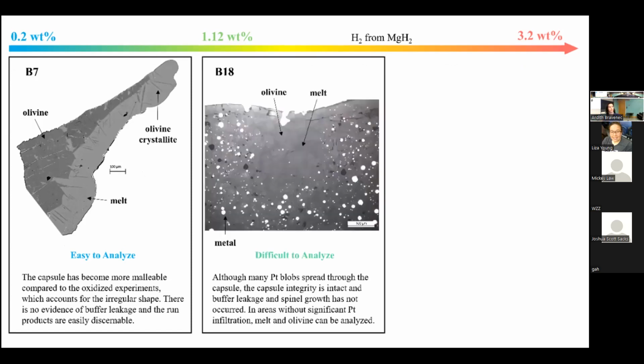Then things got a little bit more iffy when we upped the hydrogen content to above 1 weight%. Now, I mentioned before we use platinum capsules because they're relatively inert. They're not supposed to react with the materials inside the capsule. And their melting point is very, very high. So they shouldn't melt during these very high temperature experiments either, especially under pressure. But what you can see here is that the platinum is reacting. It's actually forming platinum hydrides, these little micro nuggets that can then infiltrate the capsule and contaminate the sample so that you no longer have large spaces of olivine or melt to analyze.